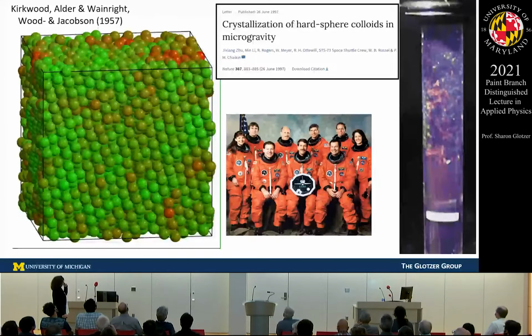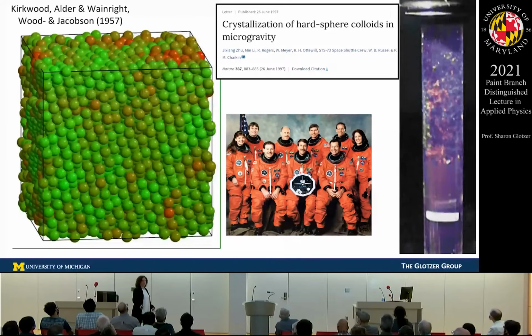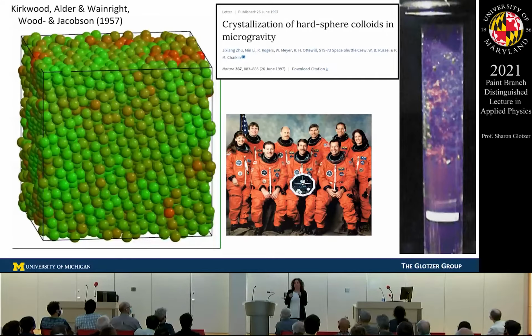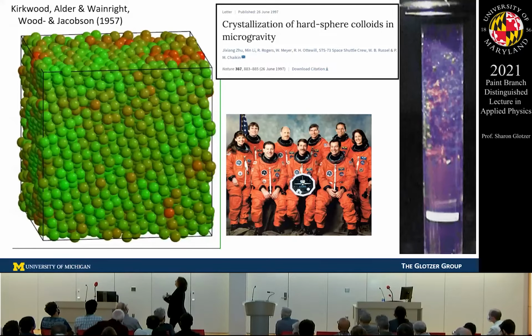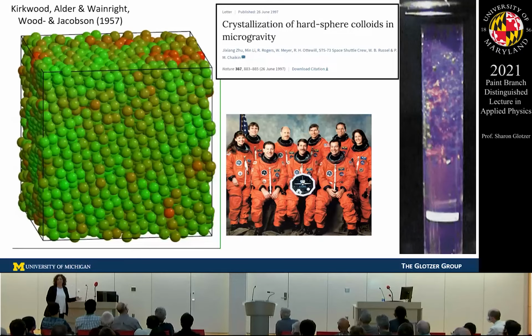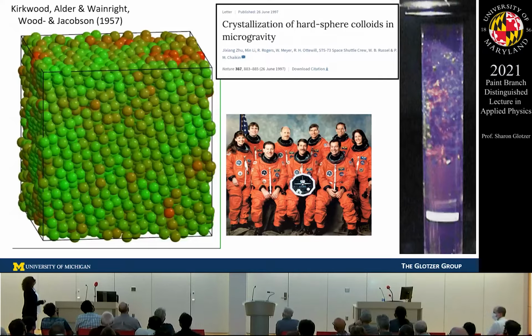And in fact, the way that I understand it when I go to these Gordon conferences on the physics of liquids, this was something that was argued over for a long time, that entropy could possibly order hard spherical particles. Of course there were simulations, but people were like, they're just simulations. They're not real. We don't believe that. And so this team, led by Bill Russel and Paul Chaikin at Princeton, in 1997, their experiment got to fly on the space shuttle, and so the crew of the space shuttle that did these experiments for them are authors on the paper.